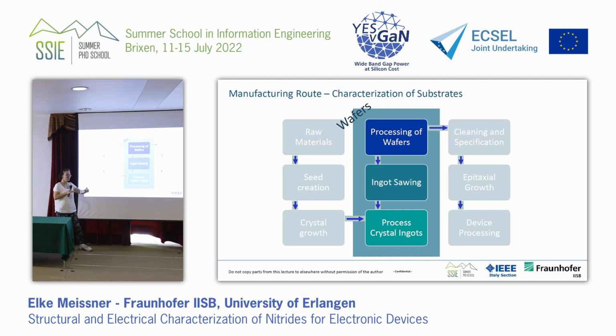So imagine you order a material, a brittle material, atom by atom, and then you put brute mechanical force to it, and you grind it round. This is crazy. This is really crazy. It works. This is also done for silicon, big ingots, like 400 kilograms. This is really mechanically round trimmed.